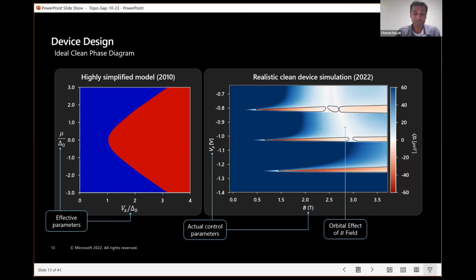Okay. One simple question. Is it possible to have FFLO because you apply the magnetic field in the x direction? Yeah, this system has strong spin orbit coupling. So as a result of the strong spin orbit coupling, the magnetic field is not large enough to induce an FFLO state in the aluminum, and it doesn't induce it in the semiconductor because of the large spin orbit coupling. I see. Yeah. Okay, thank you.